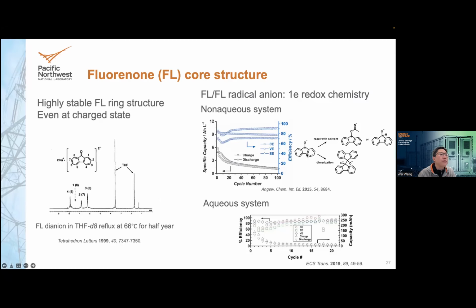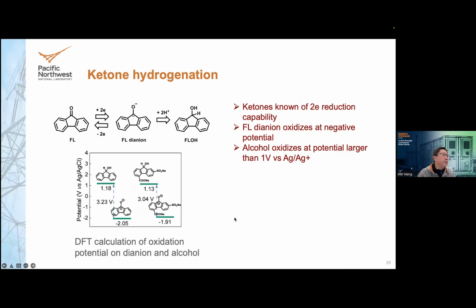There are attempts to put it in the non-aqueous system. They can cycle, but the capacity quickly fades. And in the aqueous system it is even worse. Within 5, 6 cycles, the capacity almost dropped to 0. The issue here is the reversibility.